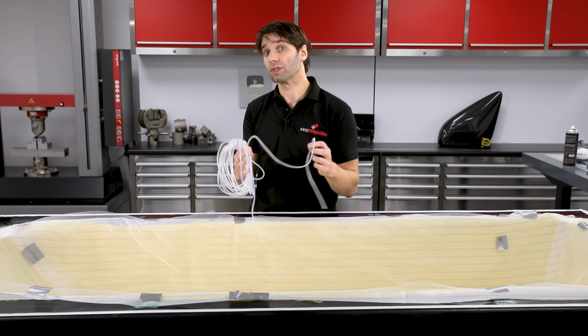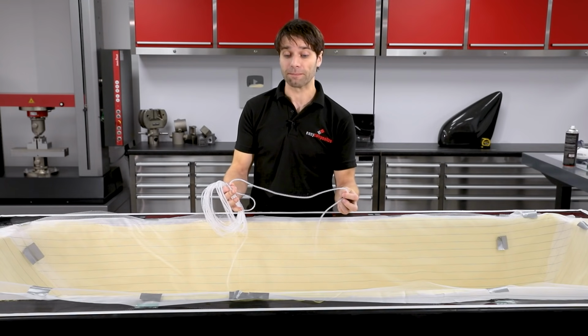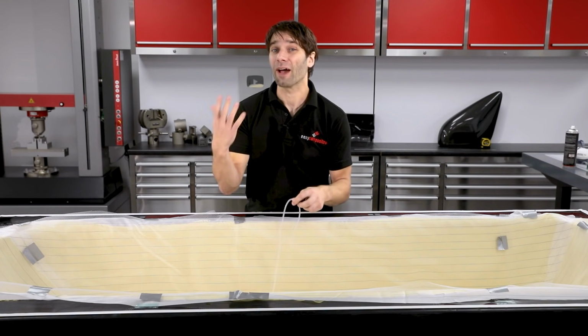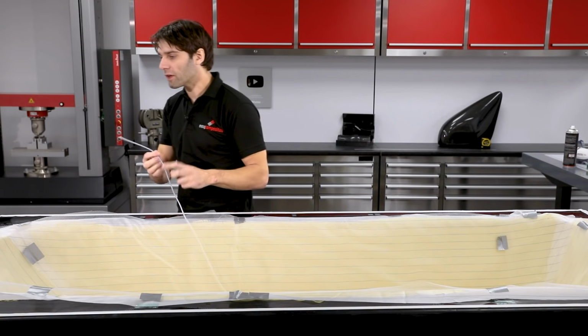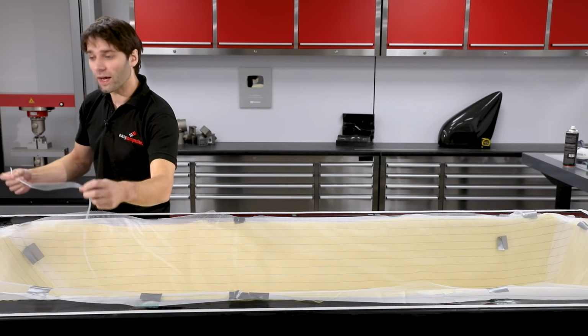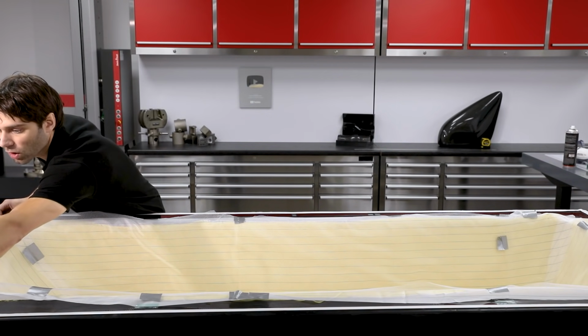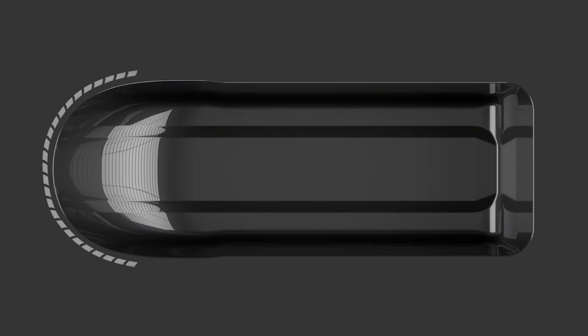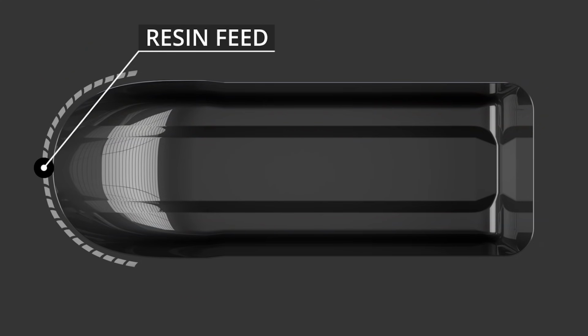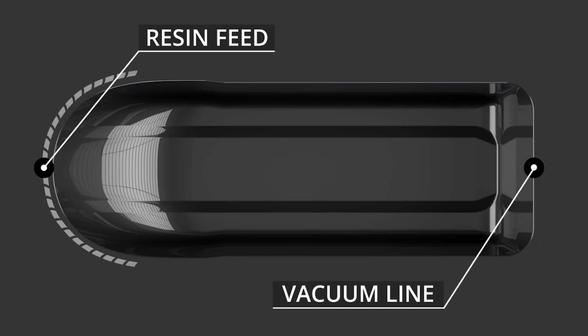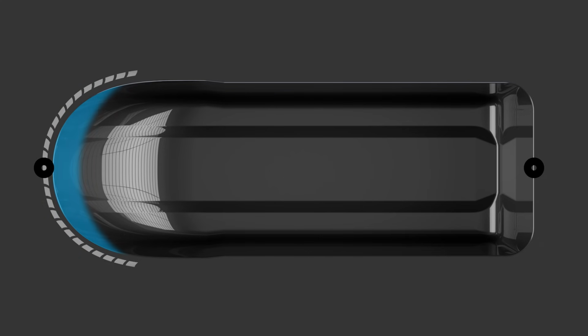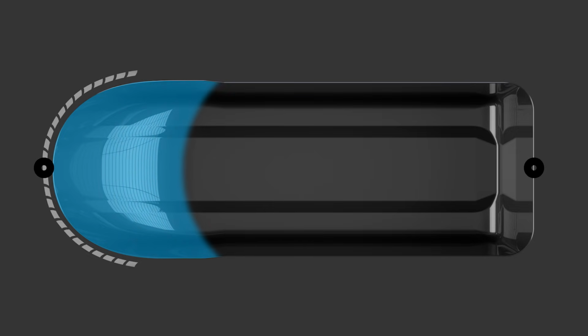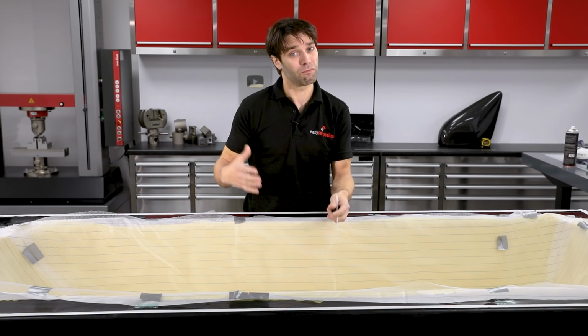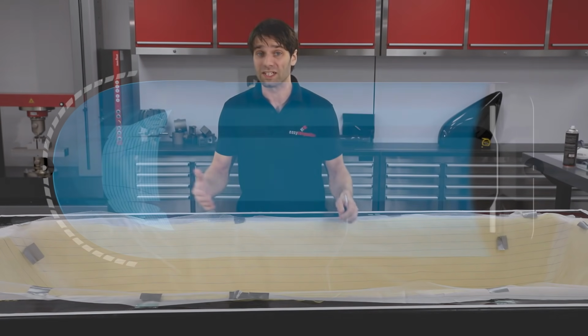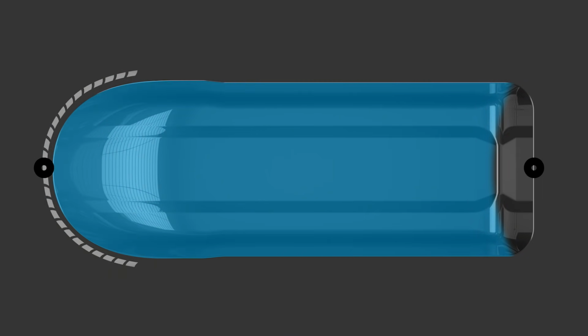There are a few simple rules you can follow to help optimise the flow of the resin. So let's look at a few examples as to how you might set this up. Probably the most obvious or intuitive way that most people would think would be to run a spiral down one end of it with a resin feed line, and then over at the far end run the vacuum point. And in this case we'd be asking the resin to flow for nearly 3 metres. Now if we did that, that would take probably around about 4 hours or so to infuse, which is much longer than the pot life on our resin. So we've got to think of ways to reduce that.